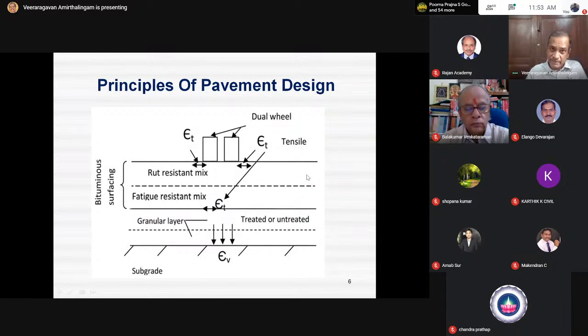But the rutting can be due to excessive vertical compressive strain on top of the subgrade, or it may be due to the bituminous mix alone. If the design is not, or the mix is not proper, it will rut. That's why I say a rut resistant mix. The mix will shear off. So don't relate that mix problem to the vertical compressive strain. But people do not consider this in design.